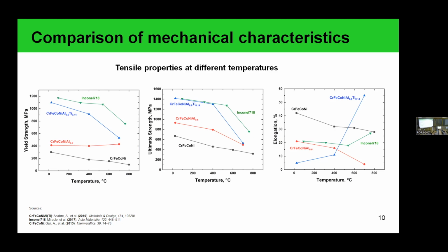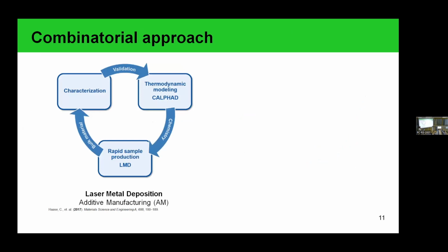And it demonstrates the same tendency for the strength characteristics in comparison with nickel alloys, and also presents high ductility at elevated temperature. But still, it demonstrates low ductility at room temperature. So this limits their application, and in the search for the required composition, there is a combinatorial approach which can be applied to optimize the strength and ductility properties of these materials. For this purpose, additive manufacturing can be applied as one of the most appropriate methods.